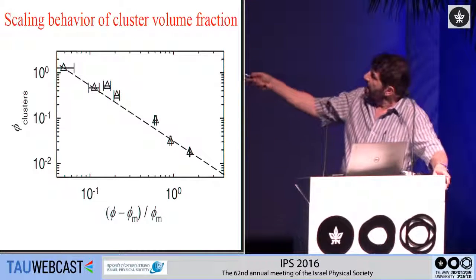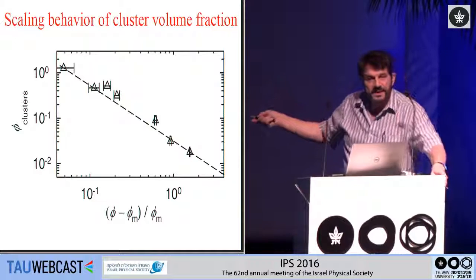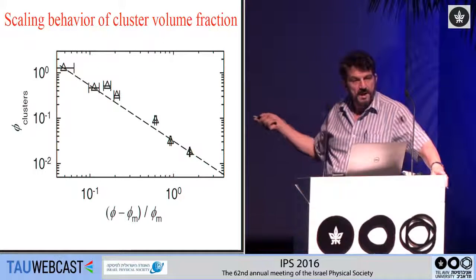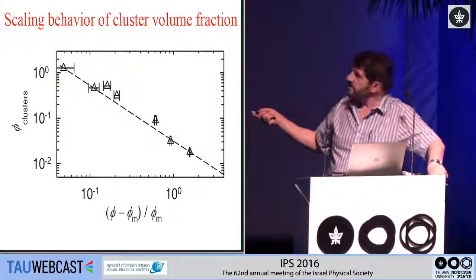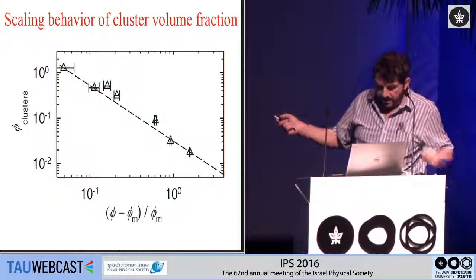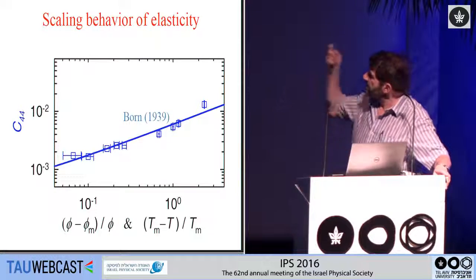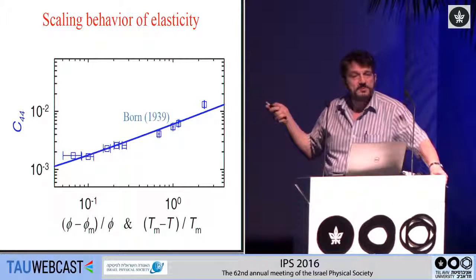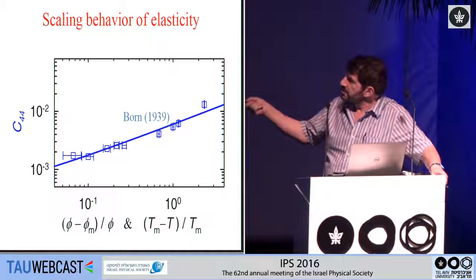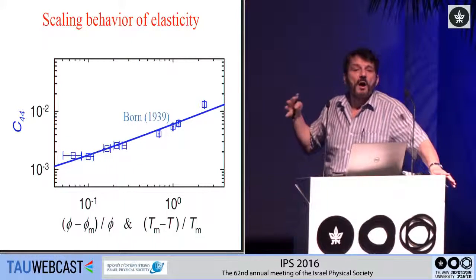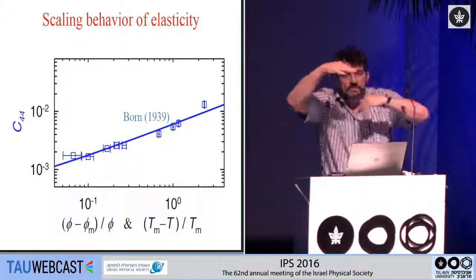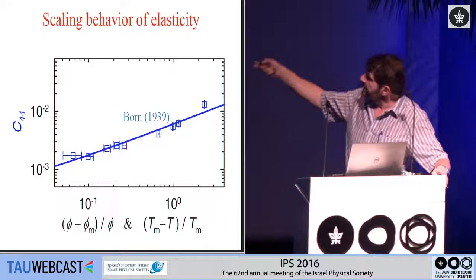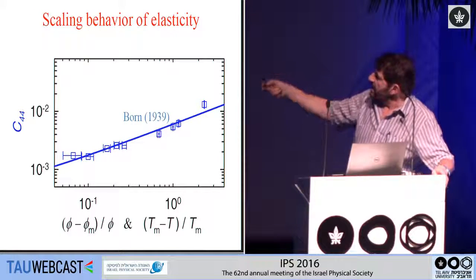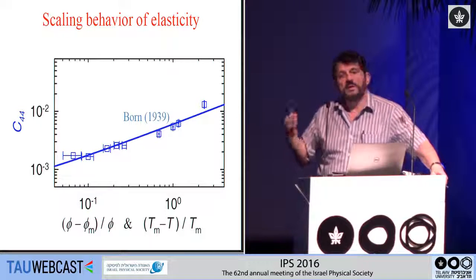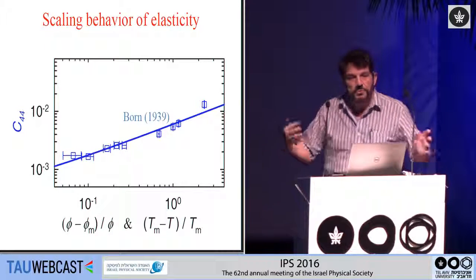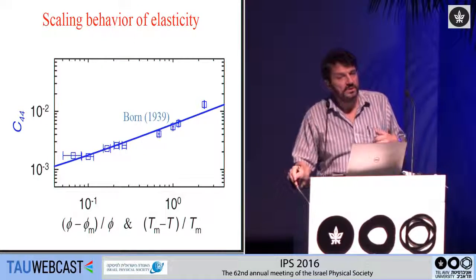If you look at the volume fraction of the clusters, and again plot that as a function of distance from the melting, you also see a power law distribution. And if you plot the elastic constant, this is in fact exactly what was predicted by Born, and we measure this by measuring the C44 elastic constant, which you can measure optically just by measuring essentially the shear of neighboring particles. You again see this scaling-like behavior. In fact, this was inherent in the predictions of Born, although he didn't recognize it himself. If you replot his data or his calculation, you see the same things.